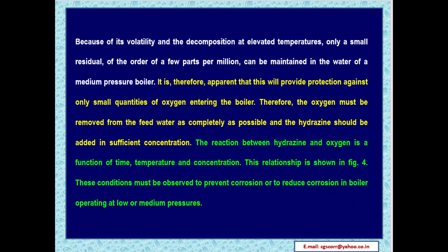Therefore, the oxygen must be removed from the feed water as completely as possible, and the hydrazine should be added in sufficient concentration. The reaction between hydrazine and oxygen is a function of time, temperature, and concentration. This relationship is shown in figure 4. These conditions must be observed to prevent corrosion or to reduce corrosion in boilers operating at low or medium pressures.